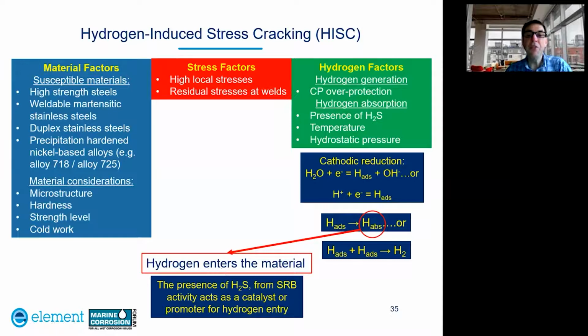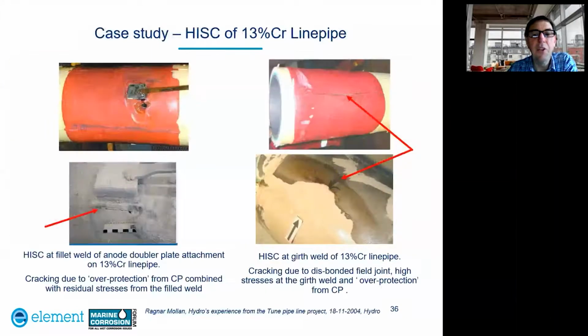So an important factor to consider is the presence of hydrogen sulfide from sulfate reducing bacteria, which can act as a catalyst or promoter for hydrogen entry. So I just want to look at a couple of case studies on HISC. So the first is on a 13% chrome line pipe. So on this example, you can clearly see this crack at the fillet weld on a 13 chrome line pipe.